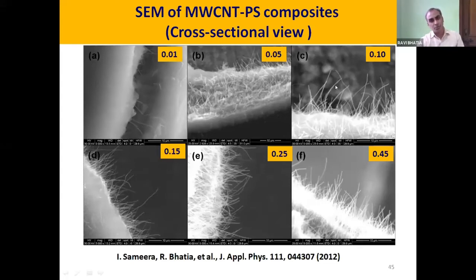So these protrusions help in the field emission of the electrons from the sample. Now there are one or two more important points: the base of your setup should be conducting, and the electron can be injected through the bottom of the electrode, which, by applying a high electric field on the top, ejects the electron from the tip of these protrusions.